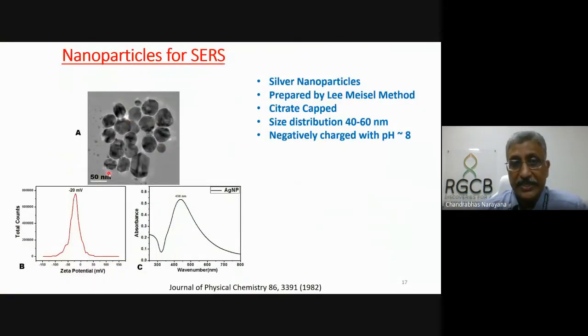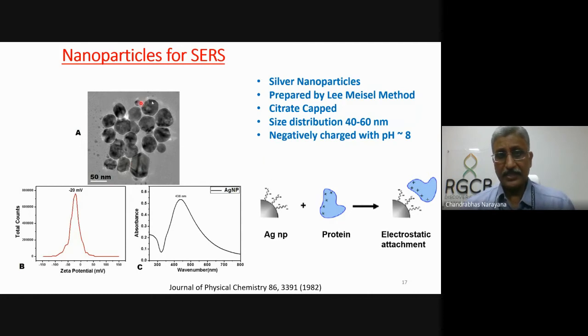And you can here see that most of our experiments with protein, we use nanoparticles of silver, which have a size varying around 50 to 60 nanometers. And that's what most of the times we use. And this is citrate reduced, because citrate is easy to dislodge by the protein. So that is why it has a charge dependence. So this is negatively charged. So most often the protein actually comes close to the nanoparticle with the positive charge. So the positive charge is very important for it to absorb onto the silver nanoparticle.